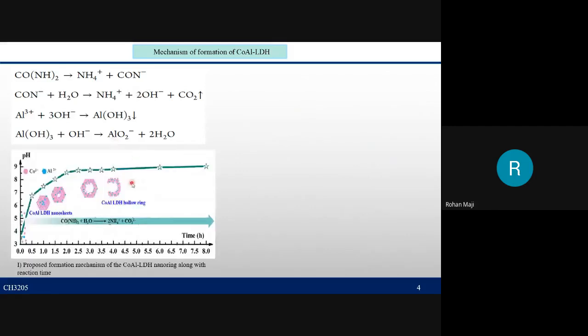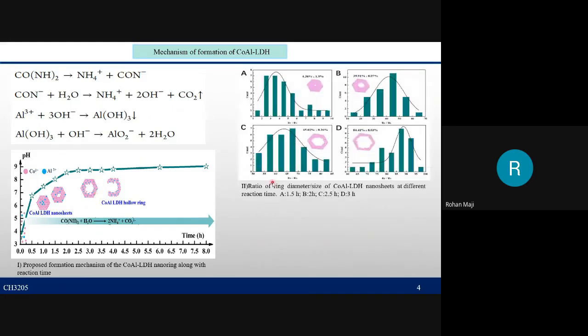Now, as we can see here, after 2.5 hours of reaction, the pH becomes almost constant, and at 1.5 hours, the central hole started to grow at approximately pH 8. But the question now is how much will this continue to grow? Otherwise, it will reach the edge. So to address that, the ratio of ring diameter and outer diameter was compared at different reaction times, as we have seen in this picture.